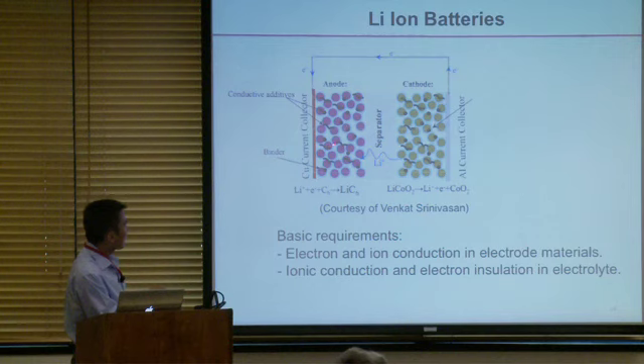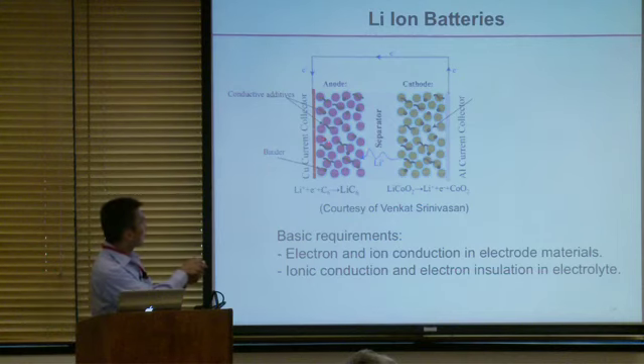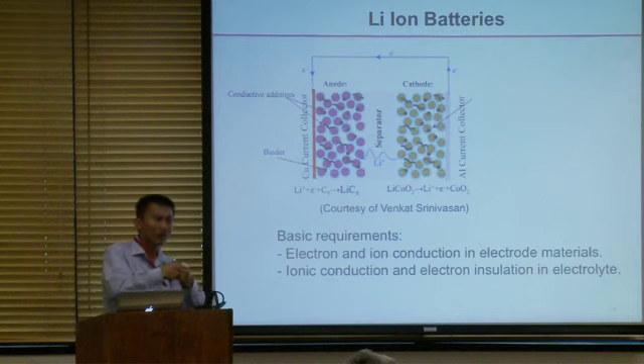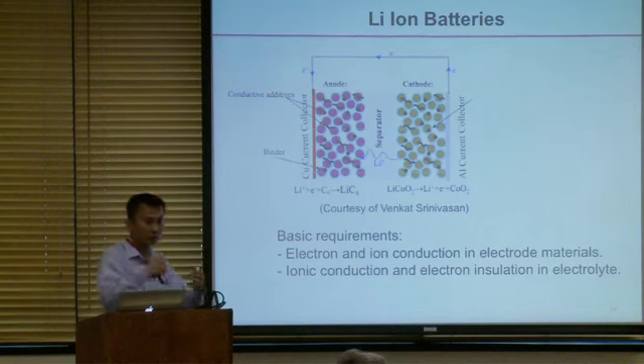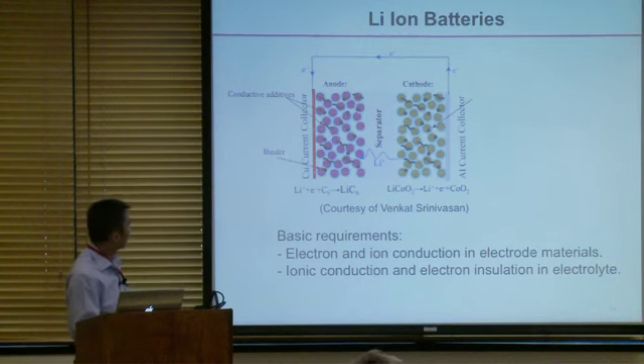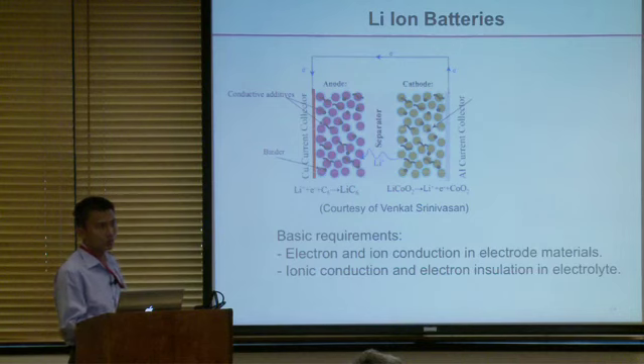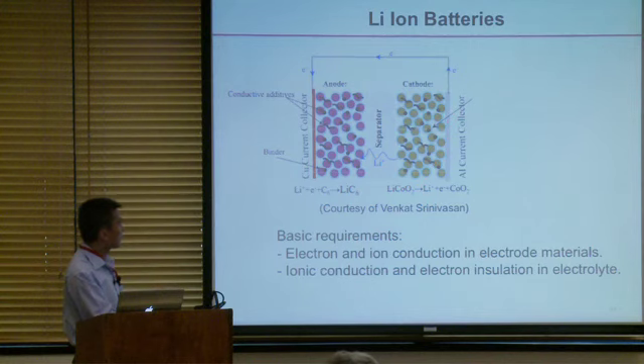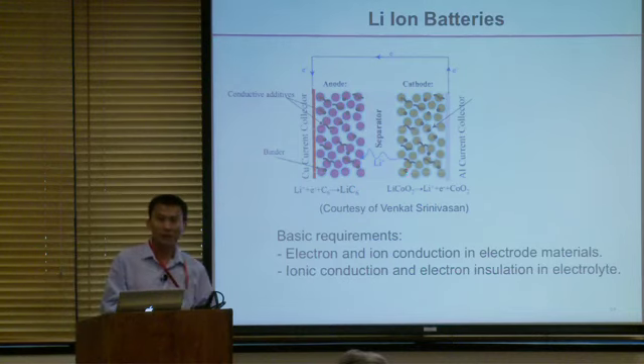You put the particles down, and as we say, you need electron and ionic conduction in the electrode materials right here. You need ionic conduction and electron insulation in the electrolyte. How do you do it? You want the particles to be conducting. You want them to be in strong contact with each other without detaching. So you use a polymer binder on the surface to get everything together. You also add in a conducting additive, tiny, very conducting particles. Even though graphite carbon is already conducting, you still need that. On the other side, for lithium cobalt oxide, you also add in particles, and to make it conducting, you add in carbon and this binder also. You need to press them very tight so they are in close contact.